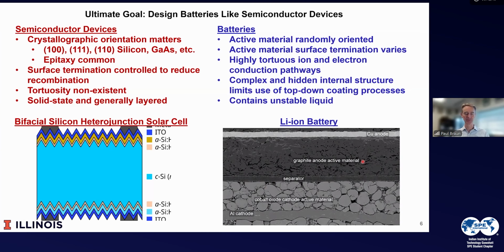If we look at a lithium-ion battery, we start out with a metal current collector, and then we basically put powders on the current collectors. We squeeze the powders together. We hold them together with binder. We add in a plastic separator. In the cathode case, we apply very high pressures and we crack the material. And so by its very nature, it is not optimally designed.